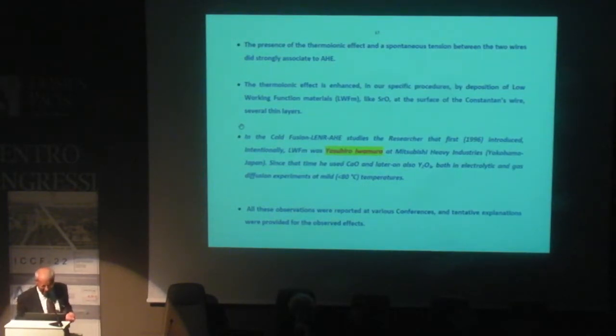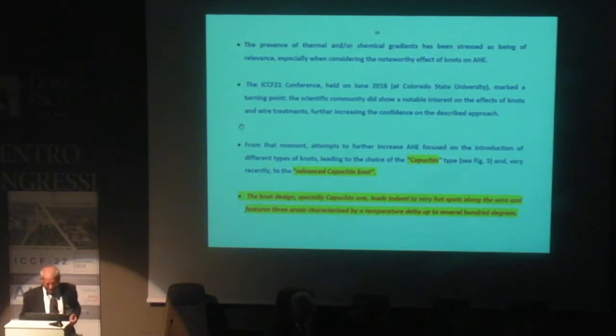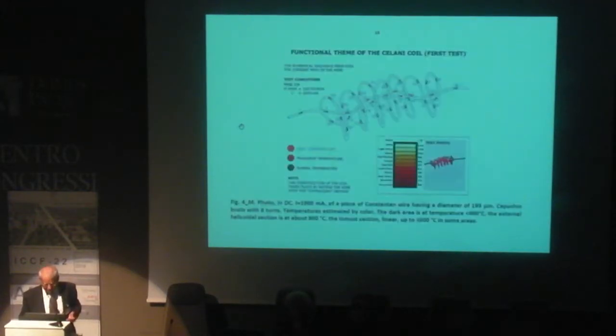Now, very, very fast about the Capuchin geometry. The Capuchin node has the peculiarity of having local thermal gradients without adding energy, but the main limitation is the number of nodes you can make, and it is easy to break. Here is the local temperature. It's a true photo. So you have a 300-400 degree difference in a few millimeters distance. In some aspects it's really ideal, but it has some limitations.